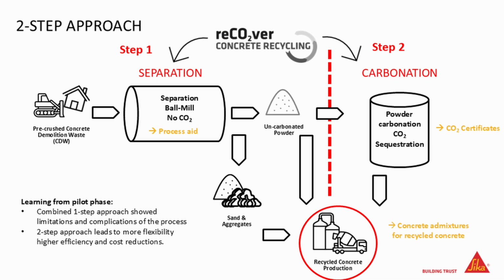The second technical aspect is that for the separation of the material, you need a very dry environment, and for the carbonation, you prefer a rather wet environment. So you always need to come to a compromise, which is not good for the separation and not good for the carbonation. When you separate it, you can focus on each step and have the perfect conditions. And the third point is that you are much more flexible, because for the first step, the main thing you need is the concrete demolition waste, and for step two, the main thing you need is CO2. And in many cases, you don't have these two materials at the same place.